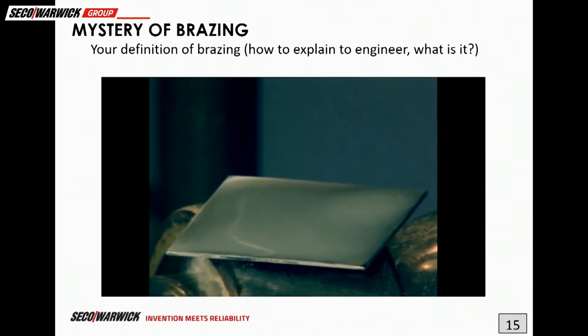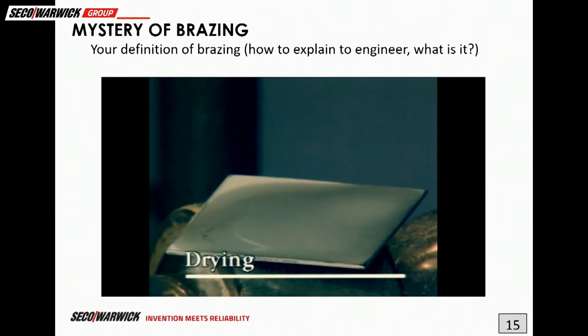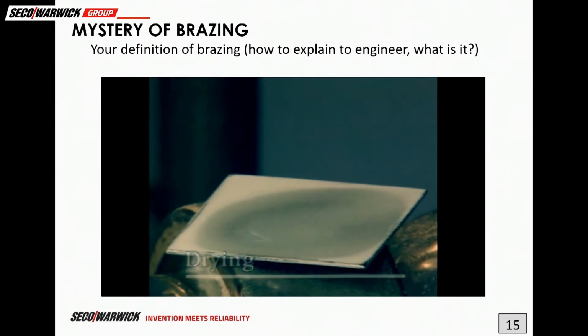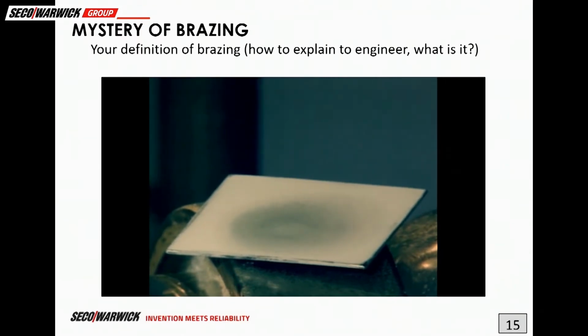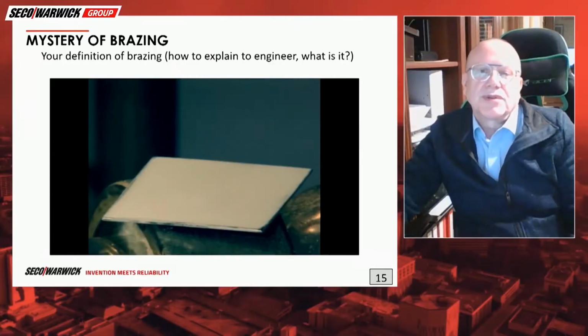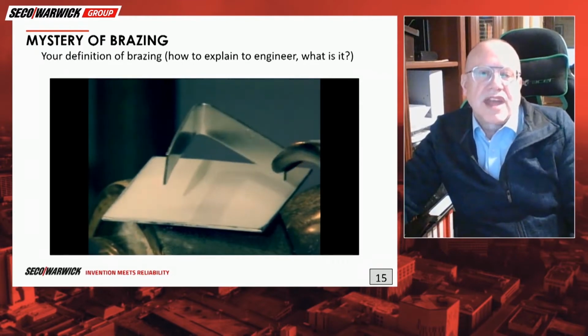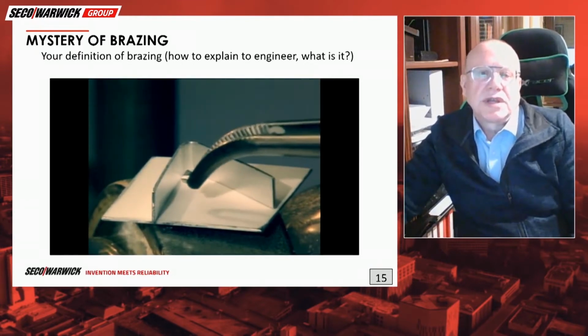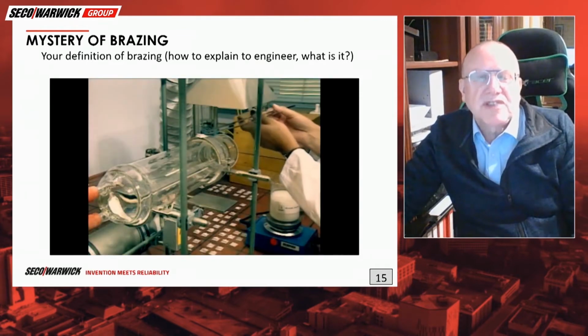Here you can see how the flux slurry is drying on the surface of the part. It is a real-time movie, and the coupon is put on top of the furnace, so you can see how it dries. It's laboratory conditions, right? Yes. It is a laboratory furnace. Flux is a substance which looks like white powder. When it's dry, it covers the surface quite uniformly. And then we put the angle on top of it and a small piece of filler alloy.